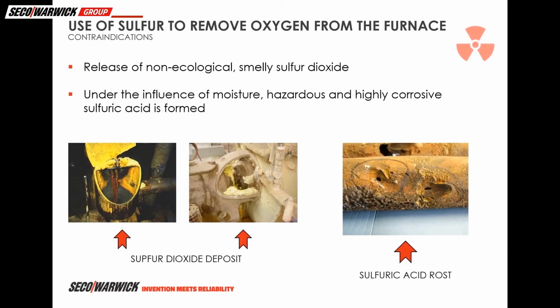In the next stage of the design, we discovered that the use of sulfur has serious consequences. Smelly sulfur dioxide is produced during the sulfur combustion reaction. Additionally, under the influence of moisture, highly poisonous and corrosive sulfuric acid is formed, which poses a serious threat to health, environment and device itself. On the sample photos you can see acid damage and sulfur deposit in the furnace. Moreover, sulfur use wasn't compliant with European regulations. Therefore, it became obvious for us that we had to quit using the sulfur and find